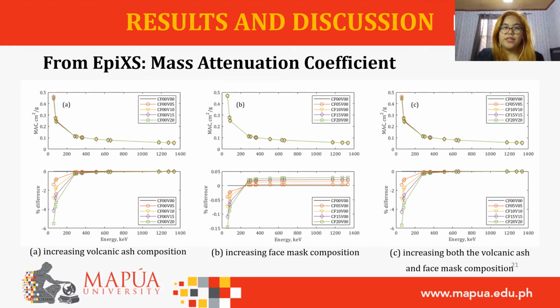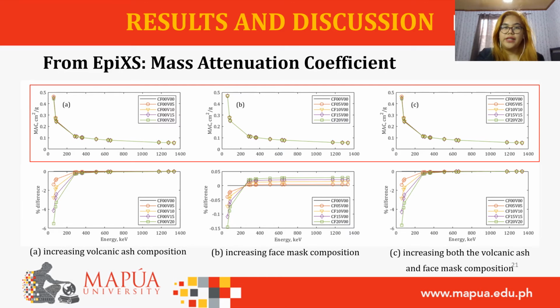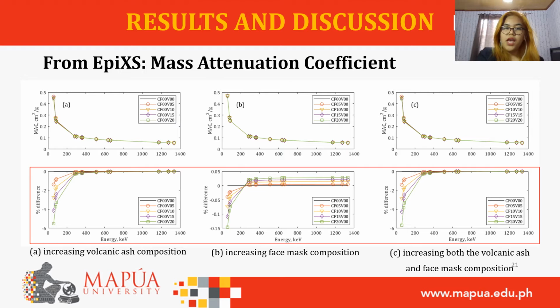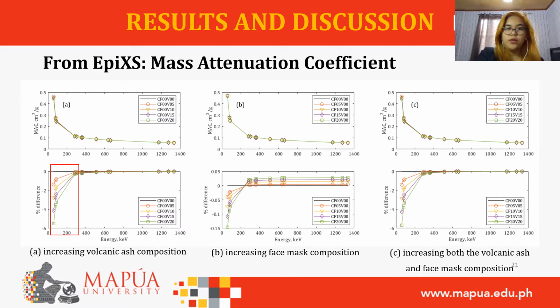Now we will present the parameters obtained from EpiXS, starting off with the MAC. The graphs in the first row are the MAC values for cases 1 to 3, from left to right, plotted against the energy in kilo-electron volts. These plots tell us that the samples are more advantageous in low-energy applications because of the high MAC values. But since all plot lines almost coincide with each other, the percent difference was obtained as shown in the second row. For case 1, the percent difference is only apparent in low energies, where CF00V05 is the most beneficial sample as it has the highest MAC values.